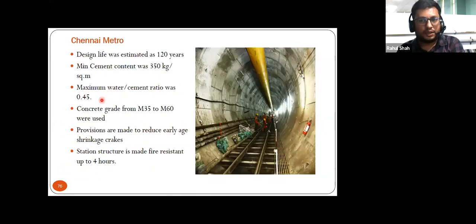Chennai Metro, it is a prestigious project for our country. So design life is, it is a design life, right? Design life is 120 years. Minimum cement content was 350 as per Indian standard. Maximum water cement ratio was 0.45. Concrete grade is M35 to M60, and provisions are made to reduce early shrinkage. And they have targeted durability of fire resistance for 4 hours.